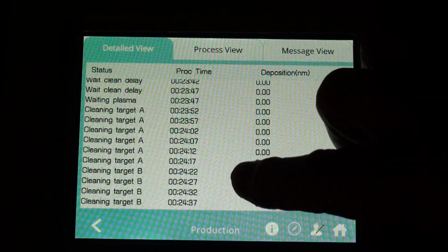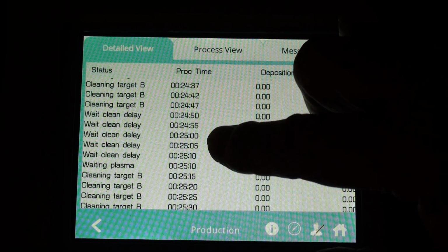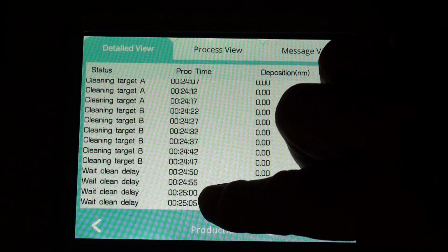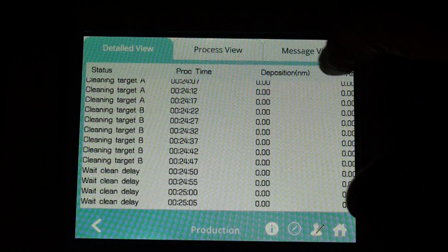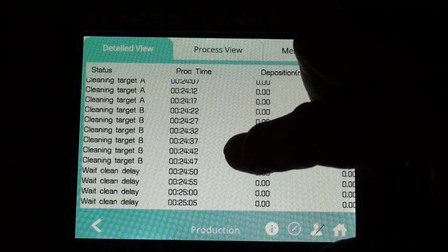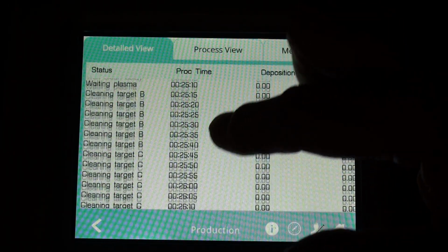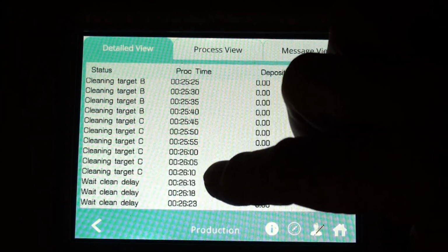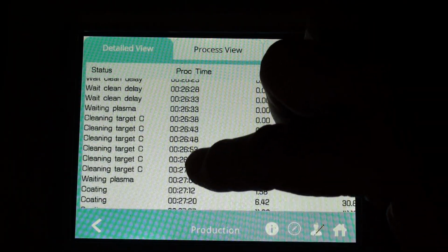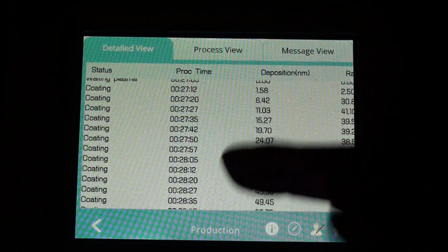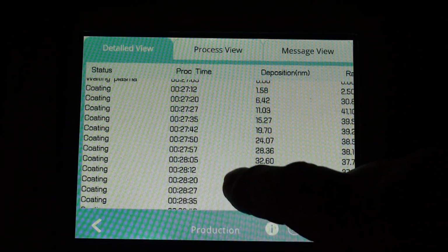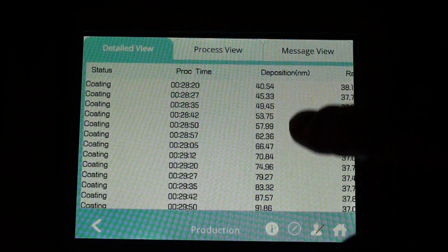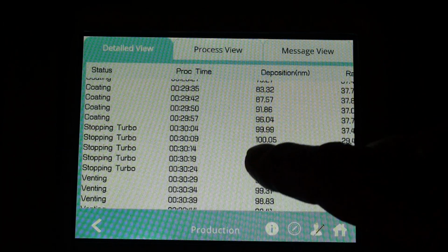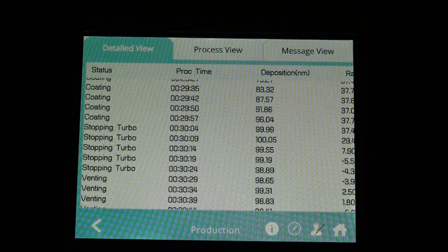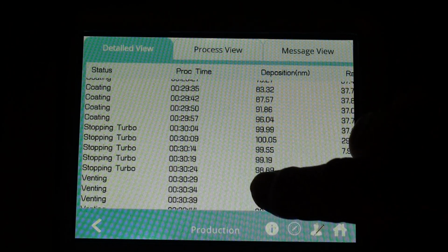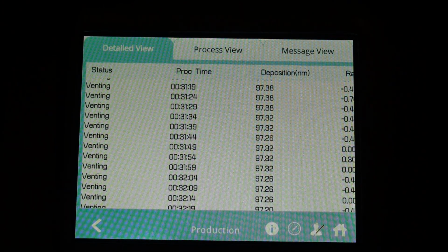Waiting plasma, it's going through its multiple targets, target A, target B. It considers target A cleaned at this point, so it switches to target B. It does the cleaning process, then switches to target C, waits delay, cleans target C again, waiting plasma. Now it gets into the coating routine, and we start coating. We can see the deposition rate going up and up. We get to 99.99 nanometers, stops the turbo, vents. The rest is relatively uninteresting.